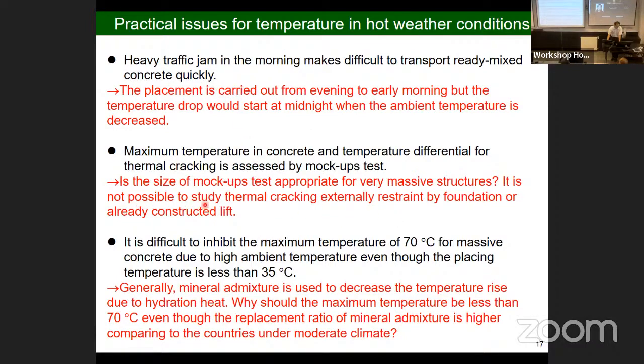And also, they always check the limitation using a mock-up test. But the mock-up test is not specified. They just make their own sites and check the effect of the temperature, so that is also sometimes not so clear. And also now in developing countries, such as Sri Lanka, Thailand, and India, they always use mineral admixture to reduce the heat. But why should the maximum temperature be less than 70 degrees Celsius, even if the replacement ratio of the mineral admixture is higher? This is about over 30% fly ash replacement. If so, later I will explain, DEF can be greatly inhibited, but they just follow the temperature. They don't care about the material. That is the issue.